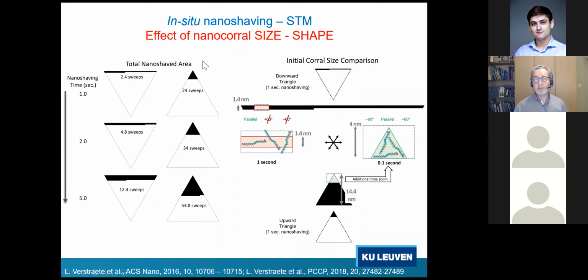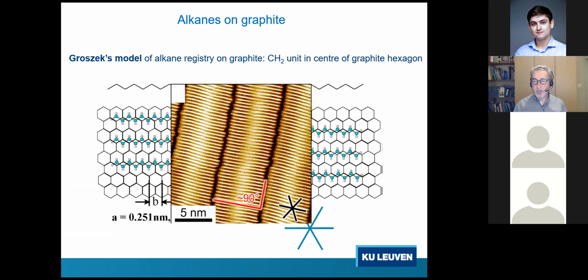This is because we affect nucleation. Imagine you start the shaving from the apex of the triangle to the bottom. If you look at the zoomed out area, a molecule, when it starts to self-assemble at the nucleation step, can adopt basically 3 different orientations. If, however, you shave from the apex to the tip, you create an anisotropic shape, and these long alkyl chain molecules will probably tend to align preferentially along that direction. So we believe that by playing with the shapes, with the speed of shaving, etc., we will be able to investigate nucleation phenomena at the liquid-solid interface.